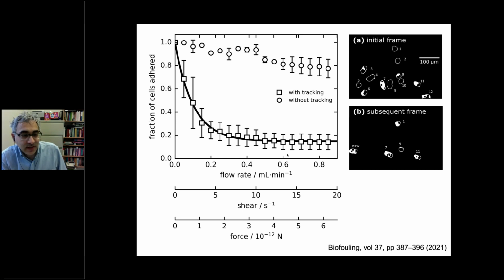So what the raw data looks like is we see what fraction of the cells are adhered as a function of the force they experience. So this 1.0 on the left-hand scale of my graph, maybe 200 algae cells are adhered. And eventually that number becomes 150, and then it's 100, and then it's 75. And in the end, you have only 10 there, and the rest are all washed away. And this is really exciting because we can characterize the adhesion strength as a function of a whole bunch of